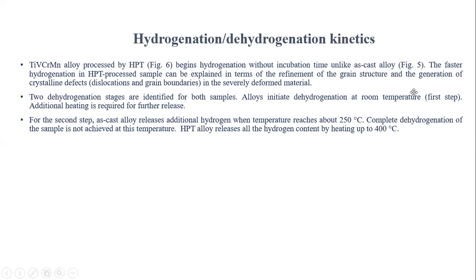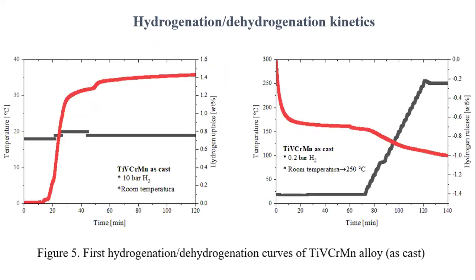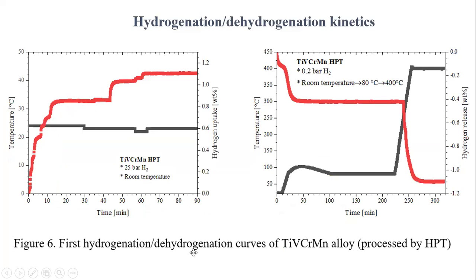Hydrogenation and dehydrogenation kinetics show that the alloy processed by HPT begins hydrogenation without incubation time, unlike the as-cast alloy, as shown in this figure. The as-cast alloy has an incubation period of about 15 minutes. In the first hydrogenation, the hydrogenation curves of the alloy processed by HPT show no incubation time. A high temperature of dehydrogenation is required to complete desorption of the sample.